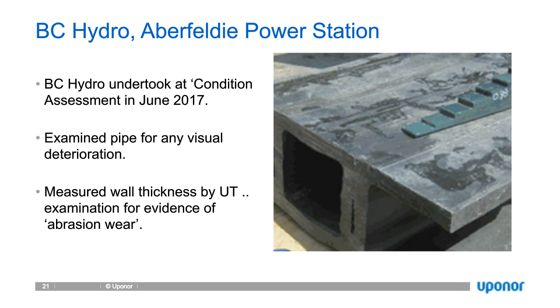So the UT equipment was checked against both the pipe and against the reference block that you also see in the photo. And it was a very accurate tool for measurement of the waterway wall thickness. We checked that at a variety of locations throughout the 2,700 feet, but no wear was observed. And a separate third-party report is being prepared for BC Hydro with respect to the wear or lack of wear.